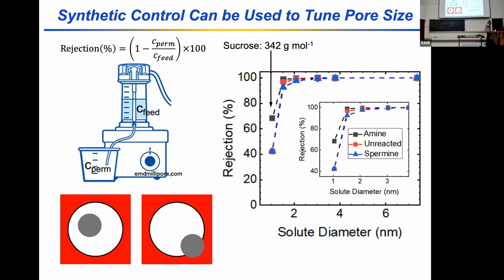This is particularly nice because this was work that came explicitly from the collaboration between David's group and our team. And we started looking at other types of copolymer architectures. Instead of using block copolymers, we use graft copolymers or statistical copolymers with oligomeric side chains, and you can actually push your molecular weight cutoff curve down to the point where you're able to filter sucrose out of solution. Sucrose has a characteristic size of about 1 nanometer, and so we're pushing this pore size down to about 2 nanometers. So we go from about 2 nanometers on the small end all the way up to about 50 or 60 nanometers on the large end.